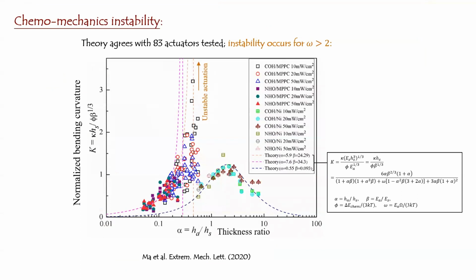So the key thing is this equation, which satisfies the mechanics-chemo equilibrium. K is the normalized curvature, the bigger, the better. And this is just a surface of alpha, beta, phi, omega, 4 variables. So alpha is the thickness ratio, beta the Young's modulus ratio, phi is the driving force, omega is the activation volume. So you just need to make sure that the omega is larger than 2.